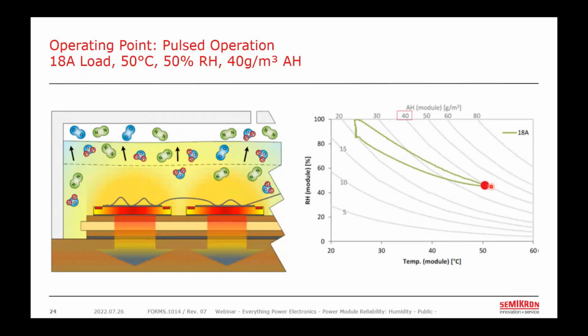But something interesting that happens here is that heat also causes the silicone gel to expand, as you see from these arrows here. And that larger volume of gel allows for more water molecules to become diffused into the silicone gel. And we've actually increased our absolute humidity from 20 grams per cubic meter up to 40 grams per cubic meter, as shown in the diagram here. We're no longer fixed on that 20 grams per cubic meter line.